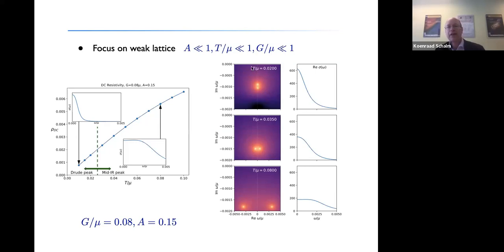If you're at very, very low temperatures, there's not one pole that explains this Drude peak. There secretly are two poles in this system, right? And what can happen is that as you increase the temperature, these two poles collide, and then once they collide, there is no longer a constraint that this single pole has to be on the imaginary axis. They can move off the axis. They can start to propagate. And that's exactly what happens. And that is what explains the emergence of this mid-IR peak. So the mystery is that there is all of a sudden, in this lattice model, a second pole. Now, where does this come from?